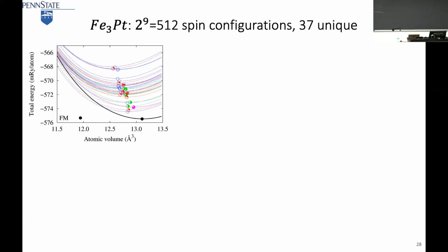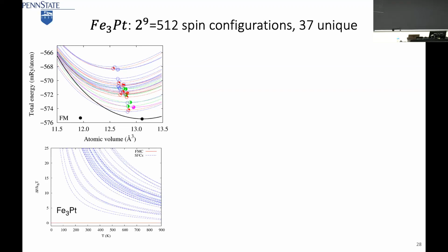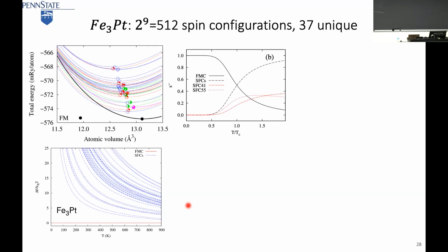And as I mentioned, we calculate the energy of all configurations. The interesting thing is that this is referenced to the ground state. If you look at the energy alone, you achieve no transition at all, right? The lowest energy state, no transformation. However, the statistical probability is beyond the static. So you put statistics on top of that one, and you find that at 0 Kelvin, it's 100% one state, but when temperature increases, the population of that one state decreases, it even goes below 50%, even though its energy state is the lowest.